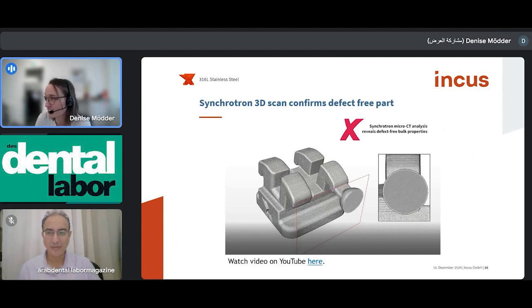In terms of porosities of the part, we reach densities above 95% of the theoretical density. We are usually more around 98%. And we don't have any porosities on the outside of the part. We had the possibility to do a 3D scan with the synchrotron, and it just confirmed that we have a defect-free part.